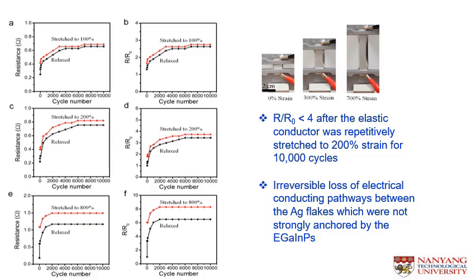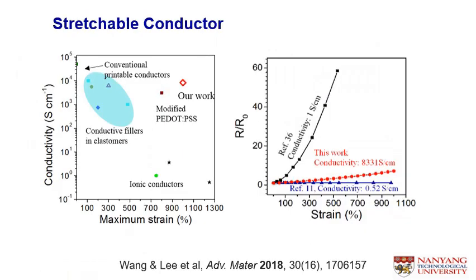The gap in the resistance is due to the irreversible loss of the electrical conductive pathway, which were not strongly anchored by the liquid metal. This stretchable conductor shows a very important achievement in terms of an extremely stretchable conductor with high conductivity.